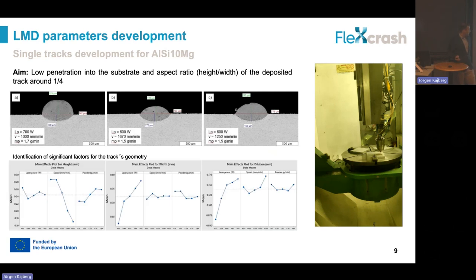From the design of experiments analysis, we can understand the influence of each parameter on the shape of the tracks that we deposit. And you can see that each of the process parameters has a very different impact on the shape. For example, speed and the amount of material that we feed through the process have a strong influence on the height of the track, while the laser power has mainly an influence on the width of the track. But very important for this project is the amount of material of the substrate that we remelt to create the melt pool on top.